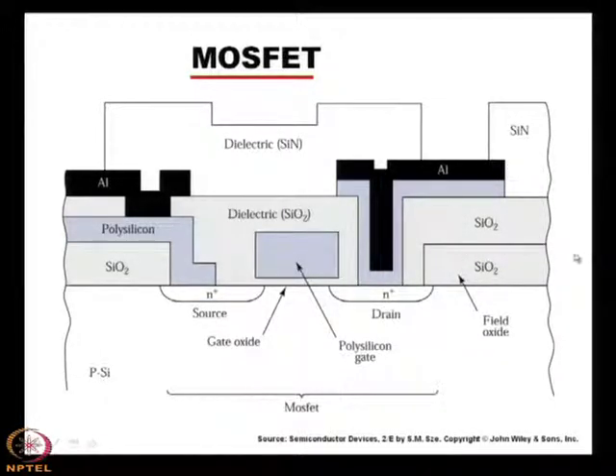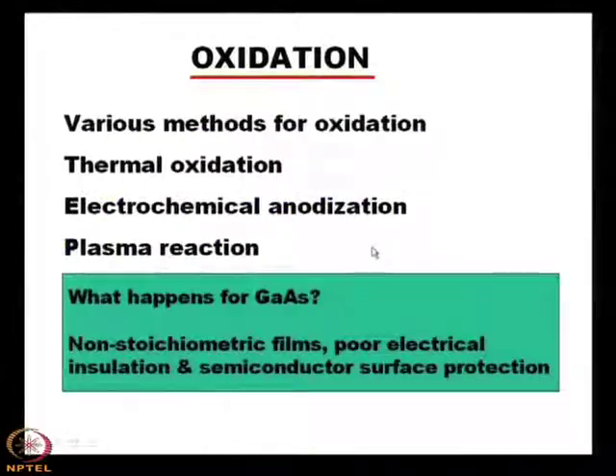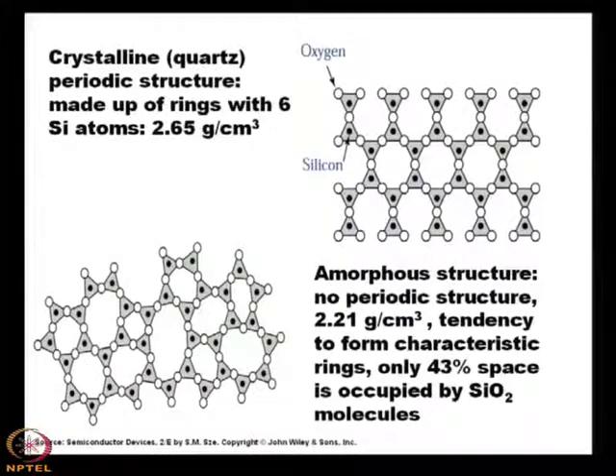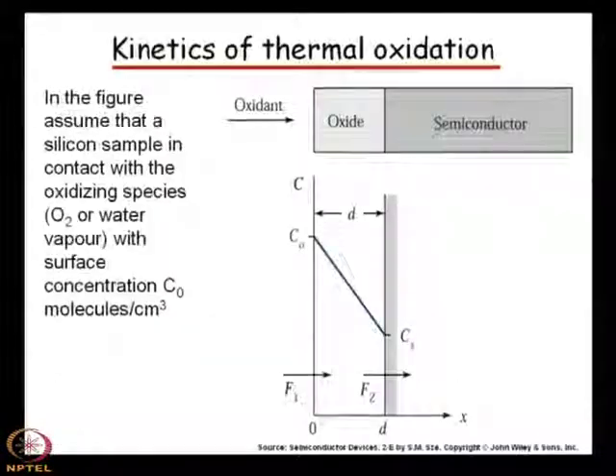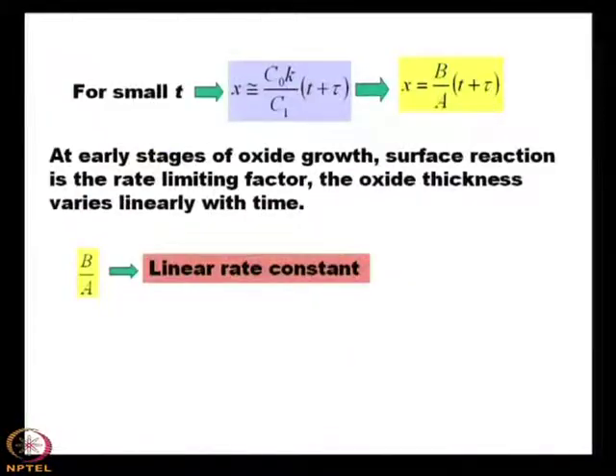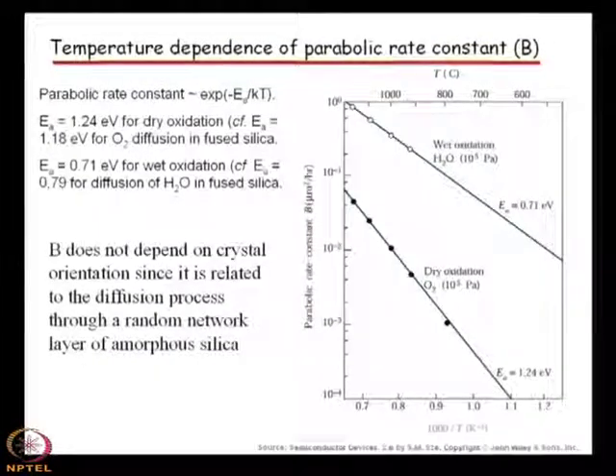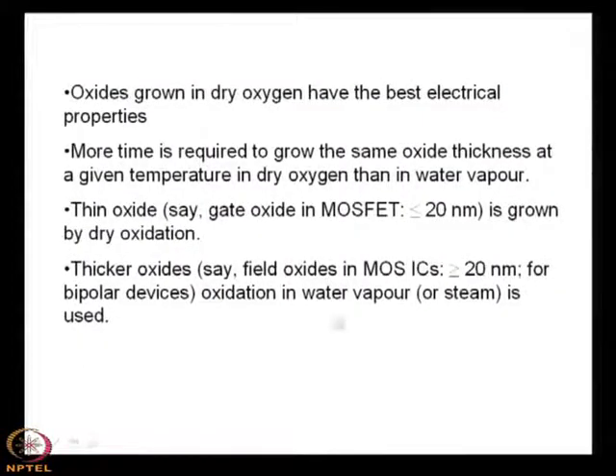It is used for the isolation or the passivation, and the less than 20 nanometer oxide is for the gate oxide to make the MOSFET. So, now with this idea we can say that for 20 nanometer we can use the dry oxidation process, and for greater than 20 nanometer we can use the thicker oxides, which is the result of the water vapor used.